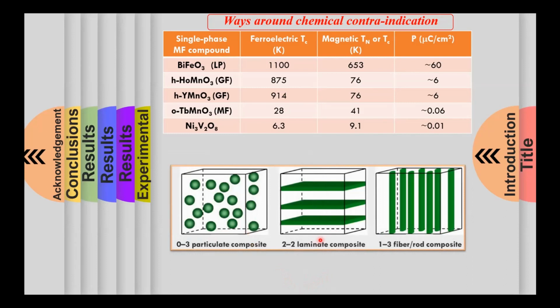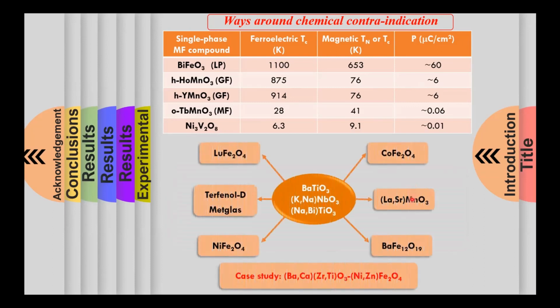So this can be achieved in various connectivity schemes like the 0-3 composites, 2-2 composites, or 1-3 composites. These are the most popular connectivity schemes. In 0-3 particulate composites, basically the particles of one phase, for example, the magnetic phase, are embedded into the matrix of the ferroelectric phase. In 2-2, we have the laminates or the multilayers. In 1-3, we have the nanofibers or the nanorods of, say, the magnetic phase embedded into the ferroelectric phase. So one can make various such combinations of composites. Here I am showing a few examples of the lead-free piezoelectric compounds like barium titanate, the KNN, or the NBT, sodium bismuth titanate.